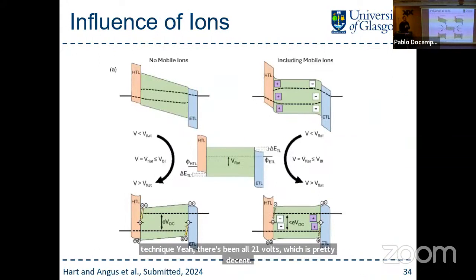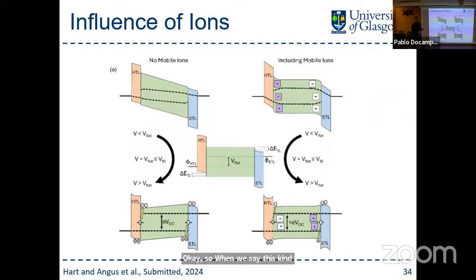Okay, so when we started doing this kind of work, we actually made an interesting thought experiment. We actually know at what point the internal electric field is zero, right? Because we can find out using the pulse technique. This is the equivalent of not having ions in the system because they're not playing a role in the electrostatics of the device. So this gives us a platform to look at what the device would be like if there were no ions in it.